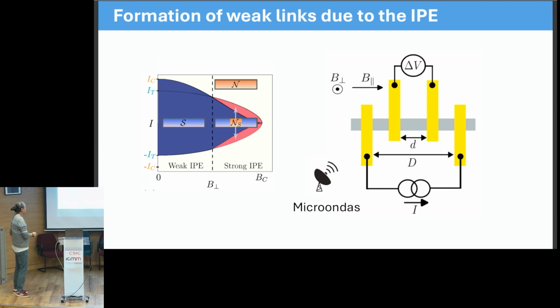So essentially, when I can suppress the superconductivity of a superconducting wire, the question is: when does this superconducting wire stop behaving as a superconducting wire and start behaving as a Josephson junction? And we believe now, by exploring the parameter space of the system, that by weakening the overall superconductivity of the wire, we can get to a regime in which we have crossed this threshold, and we create this kind of weakening. So this is ongoing work.